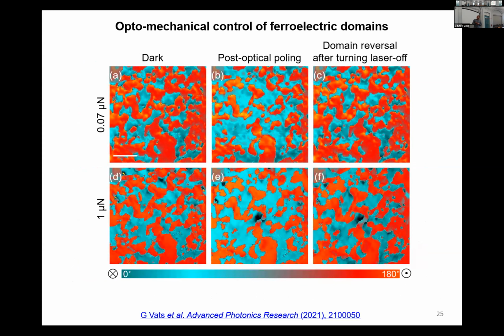These are again phase images only, not the amplitude. So you see this A image. This is acquired in dark, pristine, nothing done with the sample. And all these images are with this 0.07 micronewton peak force. I shine light. As expected, these red domains are shrinking. And then on turning the light off, it goes back. So this is something which I showed you in part A as well.